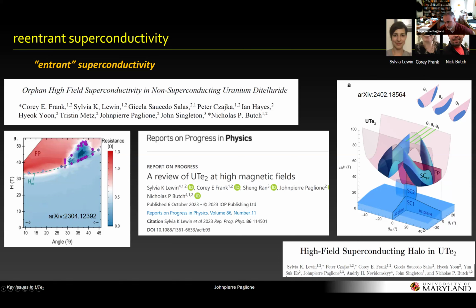Okay, and then also very recent from Nick's group, they studied the angle dependence of this Lazarus phase as you tilt the field away from the BC plane. And you can see that it's not just limited to this plane. In fact, there's some region that extends far out, showing that the superconductivity actually can persist to even higher fields.